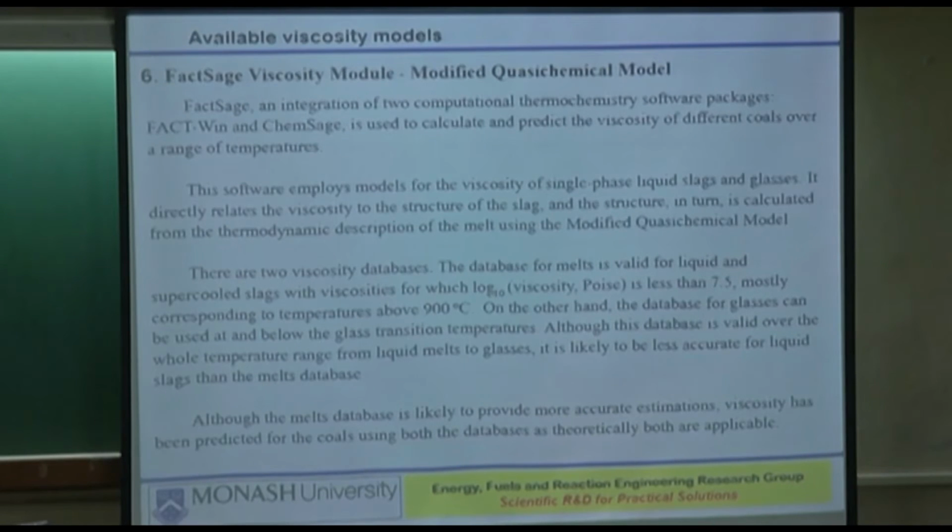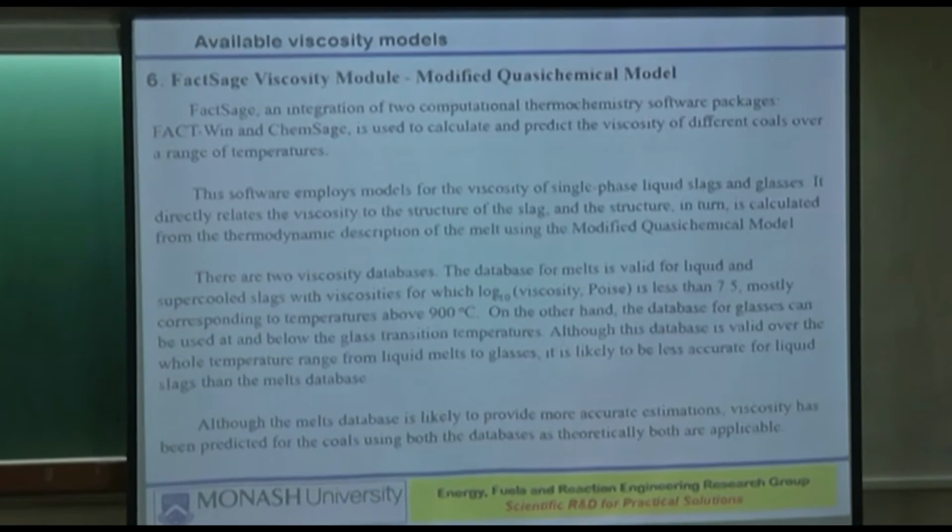So what they have done is they've taken very well characterized glasses first. Glasses are different compositions of silica and alumina and a few other things depending on the color of the glass. So in some ways, glasses are similar to slags or ashes. In fact, we buy glass from NIST, the National Institute of Standards from the US.